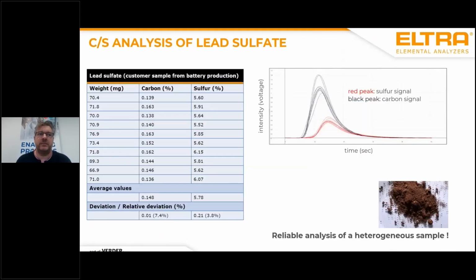For example, lead sulfate can be applied with a relatively high sample weight of approximately 70 to 90 milligrams. And you see here, we have a low carbon content of about 0.15, and we have a high sulfur content of about 5.78. And the deviation is about 7% for carbon and about 3.0% for sulfur. For the customer, this result was acceptable. It can be even better when you have very pure samples, but this was a sample from the production side, and for the customer, all these results have been found as good.